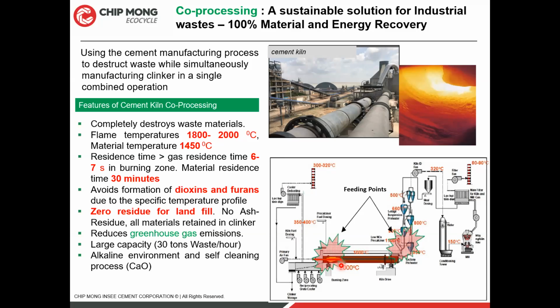Another beauty of this technology is that there are zero residues for landfill. I earlier mentioned 100% material recovery and 100% energy recovery. At the same time, if there's any small ash, that will be an ingredient of the cement clinker, which is the main semi-finished good of the cement. So there's a zero landfill process, and it reduces greenhouse gas also, because, as I already mentioned about energy recovery, we can replace some of our fossil fuels. If we burn coal, there will be CO2 emissions. Therefore, here we can avoid some of the coal consumption.